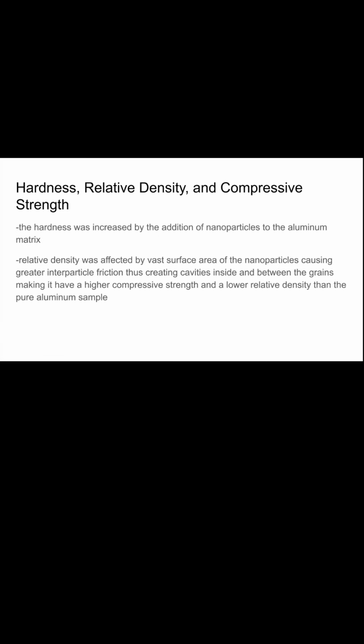The mechanical properties of hardness, relative density, and compressive strength are also greatly improved by creating this composite. The hardness was increased by the addition of nanoparticles to the aluminum matrix, and its relative density was affected by the vast surface area of the nanoparticles, causing greater interparticle friction, thus creating cavities inside and between the grains, making it have a higher compressive strength and a lower relative density than the pure aluminum sample.